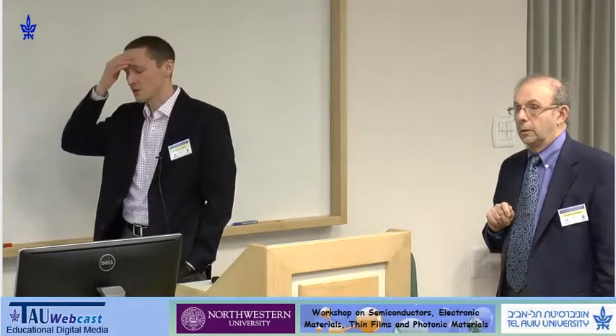So in these devices, we've done the IV characterization in vacuum, in Mark's lab, EFM in air. Yossi had some early devices to look at Kelvin probe in at least a dry environment, and that's what I would want to use as the basis for starting to look at particular mechanisms, because if we can measure the potential drop under the conditions where we're getting the motion, that would be very helpful in modeling of the temperature profile as well. We haven't done any direct measurements of temperature.